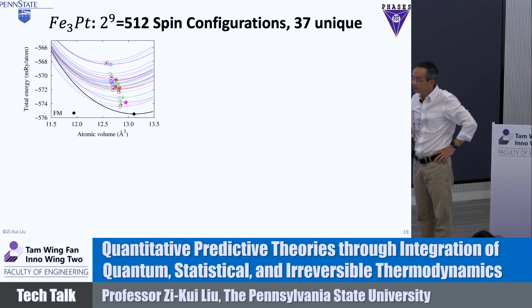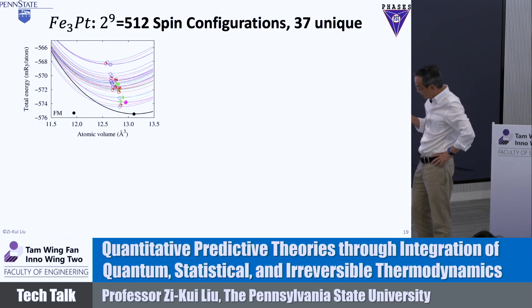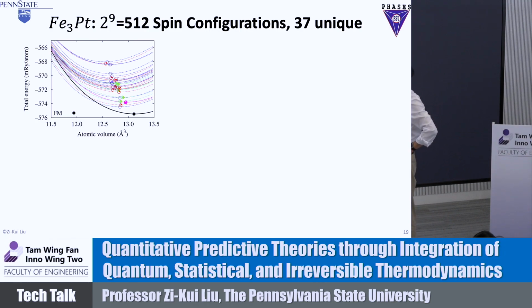We can calculate all of them at 0 Kelvin. Now you see a very interesting observation. You see all the metastable configurations we have on the left side here. They also have smaller volume than the ground state. But in the previous case, metastable has a larger volume, right? So I want you to keep that in mind. That's the origin of negative thermal expansion. It has nothing to do with the bonding becoming soft modes. It doesn't exist.